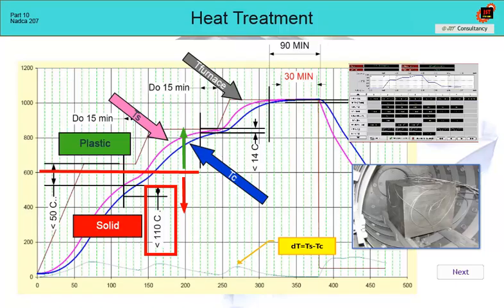The least problematic part of the heating is the area between the temperature of 650 Celsius and the austenitizing temperature. NADCA 207 says what the next preheating temperature should be, usually 800 to 850 Celsius. The prescribed temperature difference between Ts and Tc, less than 14 Celsius, is no longer due to deformations, but to ensure uniform heating of the die.